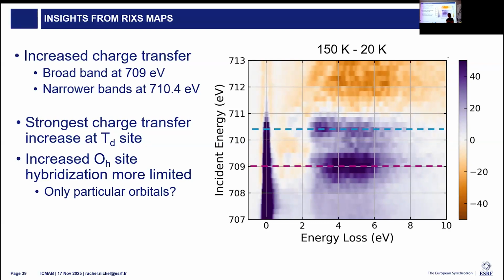The other thing that we have to be very careful, particularly for something like this, where we're subtracting maps, is any vertical energy shifts that could be happening because of shifts in the beamline. So processing of RIXS data is definitely non-trivial. It is intensity counts. So there's certain features that we would expect to change or not to change. So the fluorescence, when we take it with the two polarizations, we would expect not to have a significant difference.